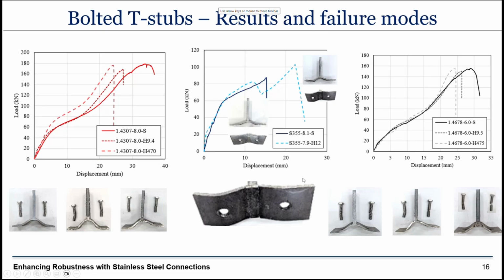For the carbon steel specimen, something weird happened. For the static case, everything proceeded smoothly. For the high-ish strain rate of 12 millimeters per second loading speed, we got an asymmetric failure mode where we got fracture on one side of the specimen, not on the weld, but right next to the weld. So for the hybrid welding, we didn't get any fracture. For the theoretically easier welding between the same material, we got a fracture in the heat-affected zone of the weld.